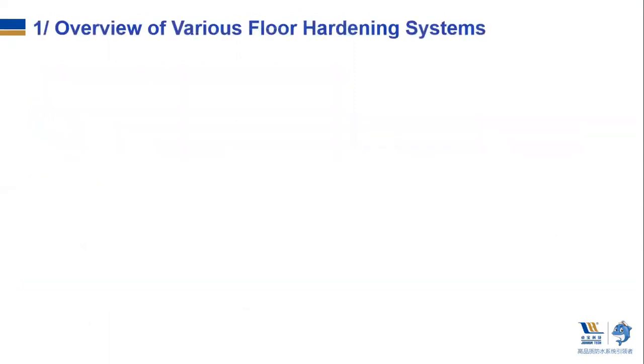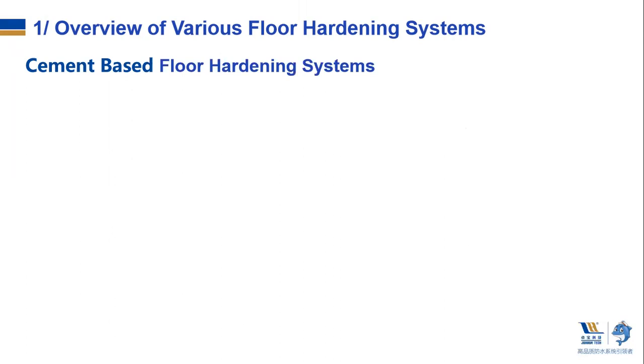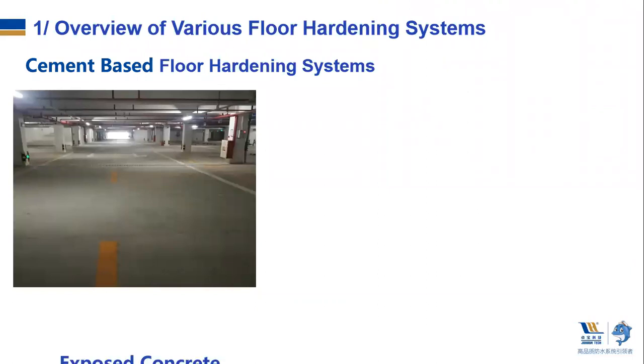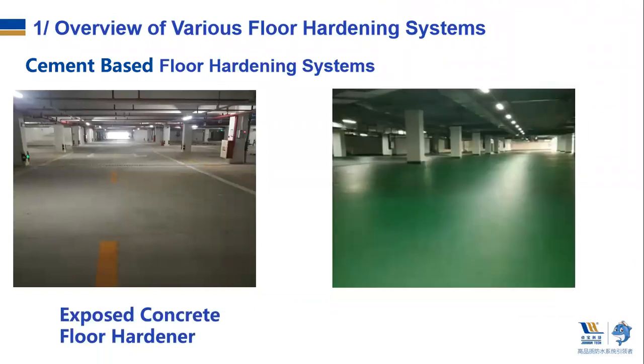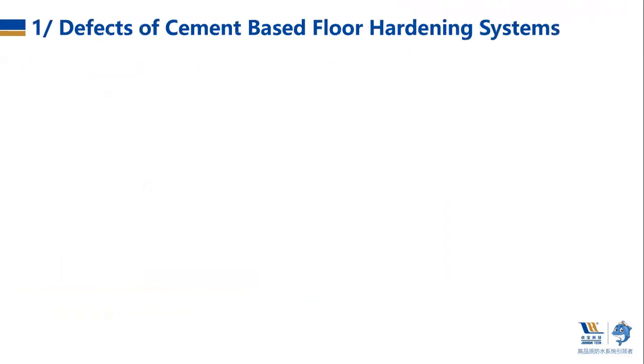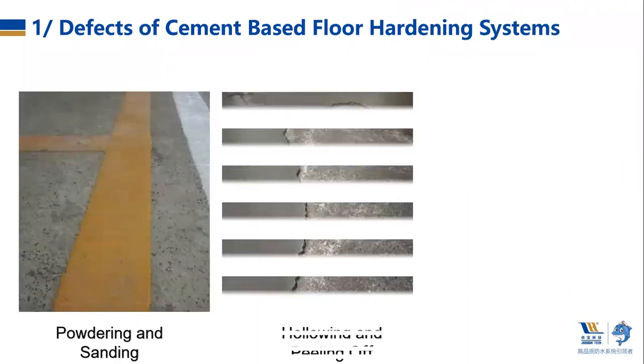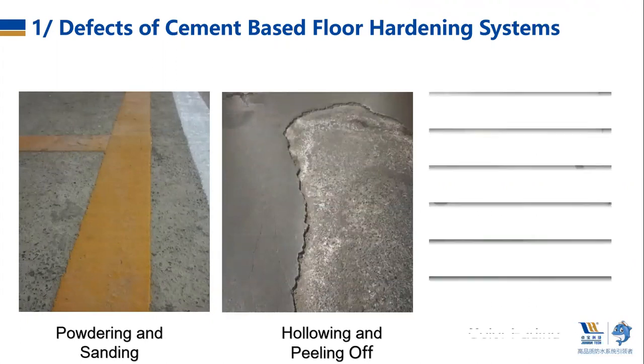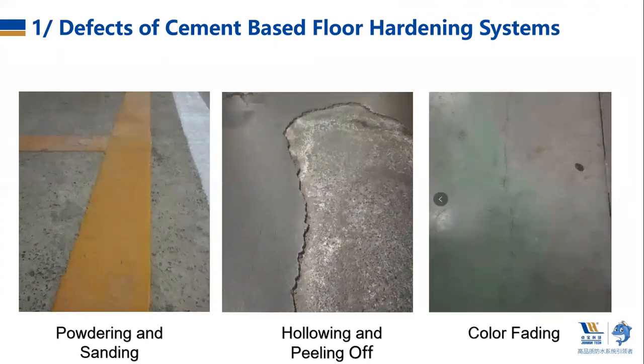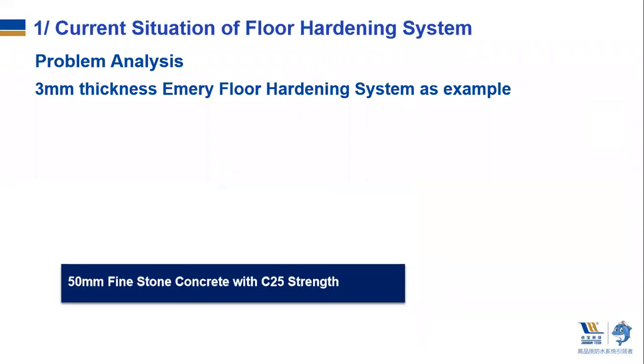Let's go through current popular floor hardening systems. The first mainstream is cement-based flow hardening system, exposed concrete and emery floor hardener. Take emery floor hardener as an example. The system looks great upon completion, but after perhaps 2 to 3 years, some even less than 1 year, faces serious problems of powdering and sanding, hollowing and peeling off, and color fading. These defects are decided by materials mechanism and application.